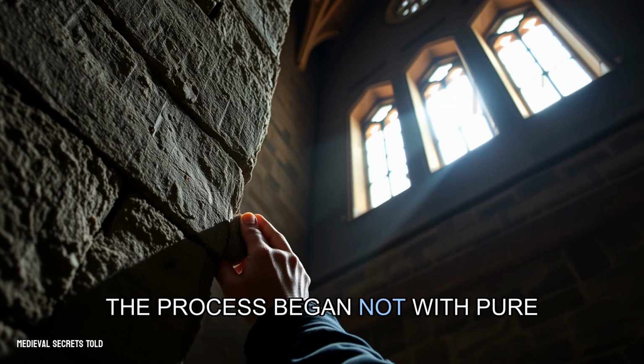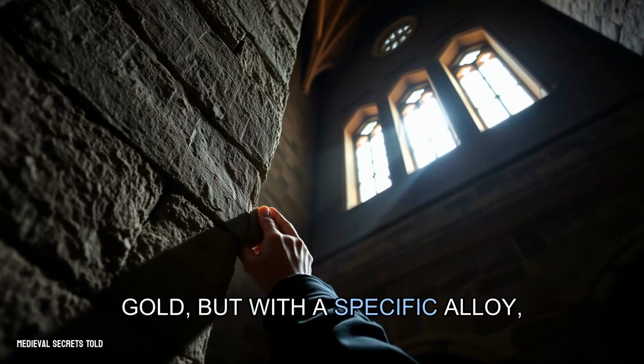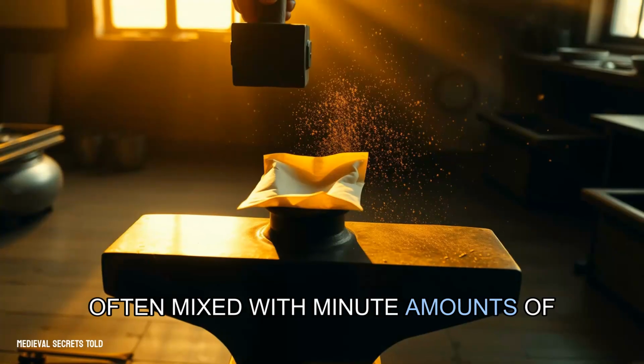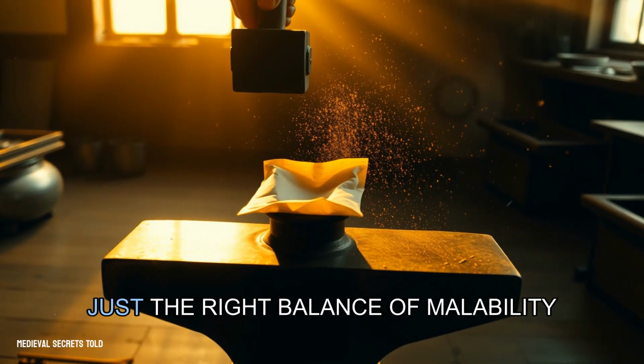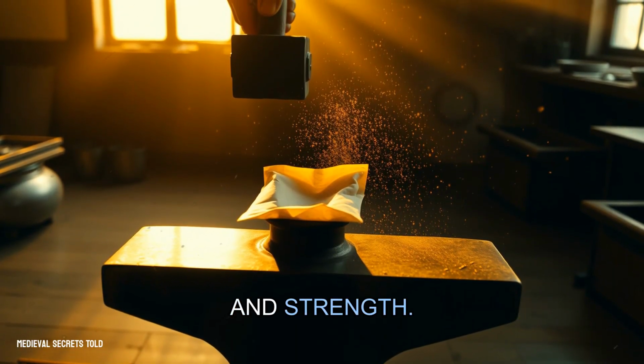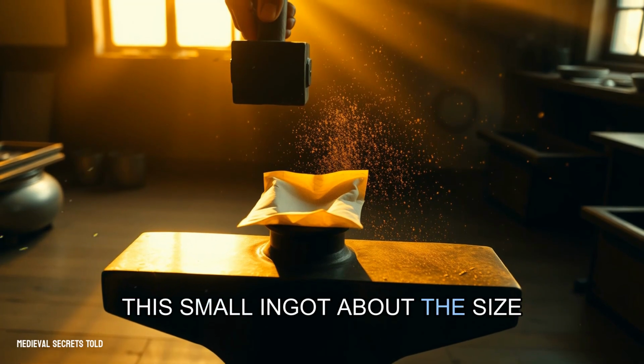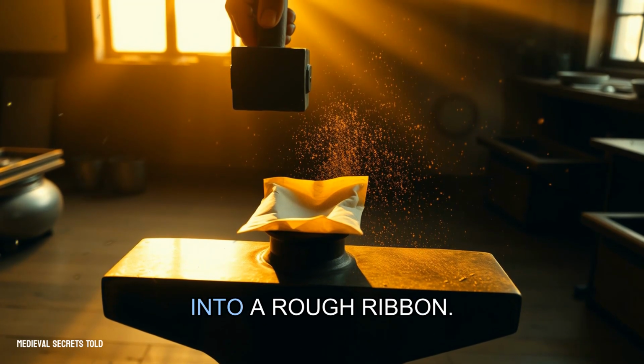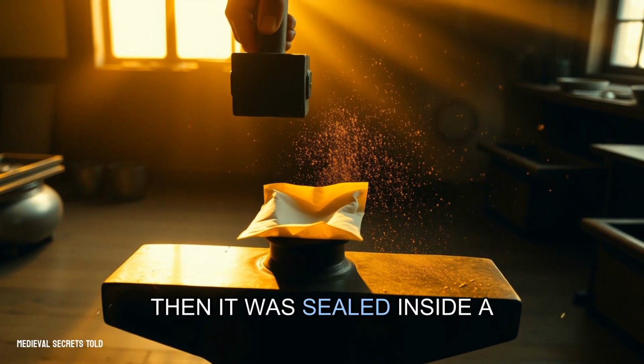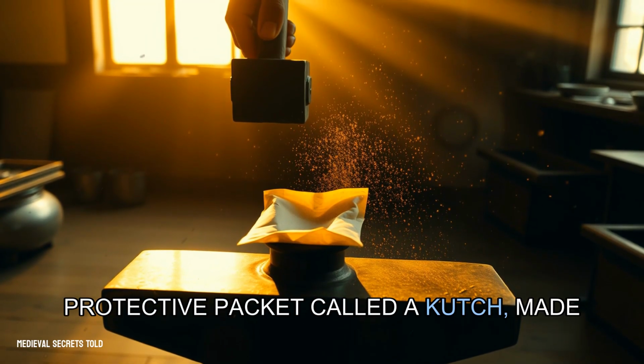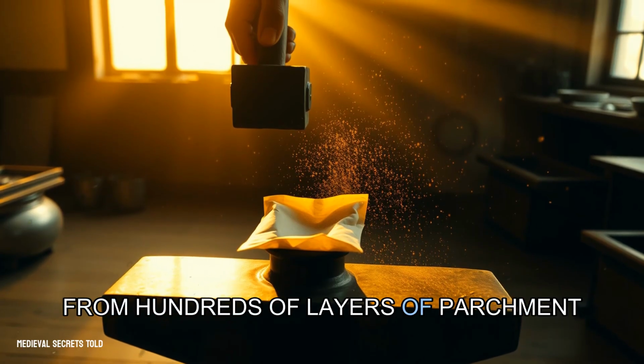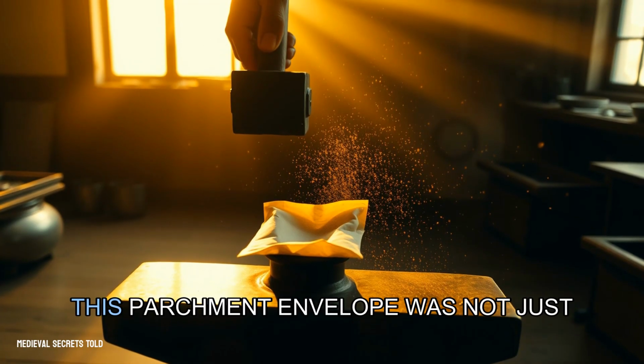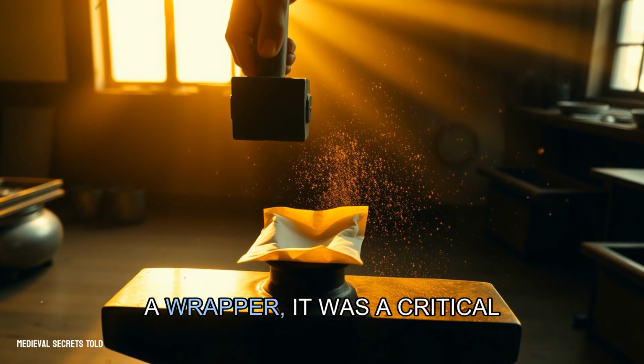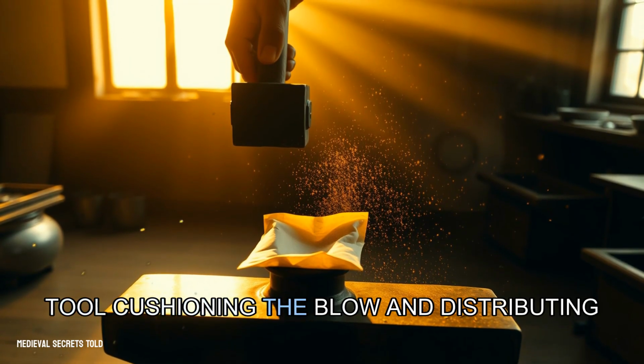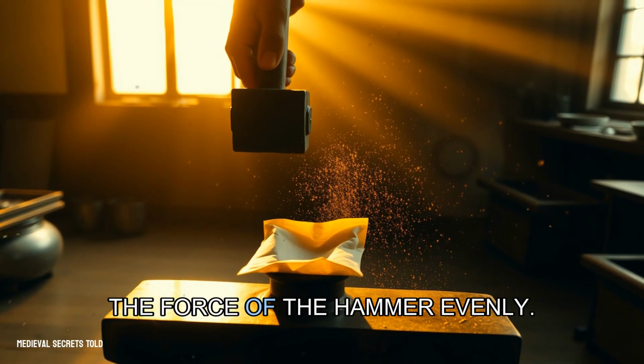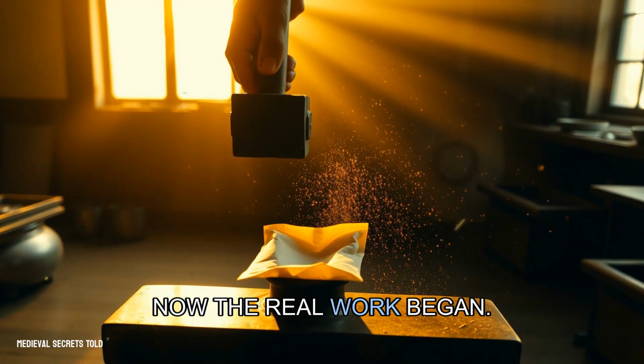The process began not with pure gold, but with a specific alloy, often mixed with minute amounts of silver or copper to give it just the right balance of malleability and strength. This small ingot, about the size of a coin, was first rolled into a rough ribbon. Then it was sealed inside a protective packet called a cutch, made from hundreds of layers of parchment or the finest vellum. This parchment envelope was not just a wrapper, it was a critical tool cushioning the blow and distributing the force of the hammer evenly. Now the real work began.